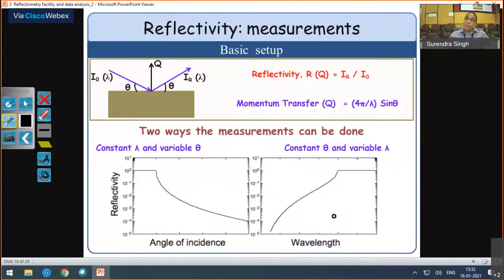Here we have pulses of neutrons of different wavelengths falling on the sample, so we have a variation of wavelength at a constant angle of incidence, and we collect the reflectivity. So this is the reactor source case, and this is the spallation source case. Though you can chop a continuous source and also vary lambda that way, it is more economic to use constant lambda and variable theta for a reactor source, which we will explain because this is what we have in our source, a reactor source at PRS.